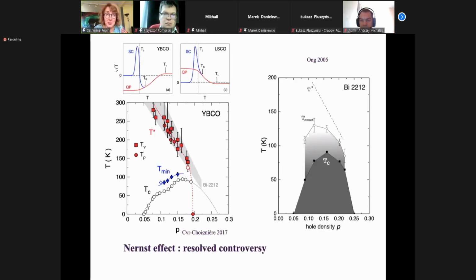It was a huge set of very good phenomenology, especially this is good for the Fermi arcs because it describes very well the closing of the Fermi arcs with the temperature. So when we reach T star, the Fermi arcs here are closing and give big Fermi surfaces above T star. But then there was a study of the Nernst effect, which is able to assess the presence of vortices, because you have a special Nernst effect, which has a special sign depending on the presence of vortices. So there was a first experiment by Ong saying that, okay, vortices are present very, very high in temperature, very close to T star. Namely, phase fluctuations should be responsible for the pseudogap.